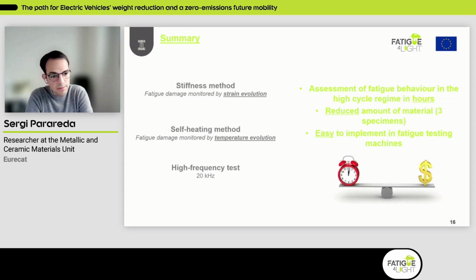And the 3 main points that you can see here in the slide is that we can assess the whole fatigue behavior in the high cycle regime in just a few hours by using a reduced number of specimens, usually only 3 specimens, and highlight once again that it's pretty simple to implement these fatigue tests in the lab at the specimen level, but maybe also at component level. And of course, it reduces the testing time, but also reduces the cost of the tests.